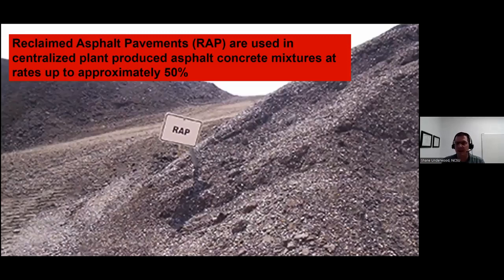Reclaimed asphalt pavements, or RAP, are generally used in centralized plant-produced asphalt concrete mixtures at rates up to about 50%. Now, the 50% usage rate is considered high RAP in the US. As I'll talk about later, the typical dosage rates are much, much lower. I'm talking here about RAP that is transferred back to a centralized plant and is mixed at that plant.